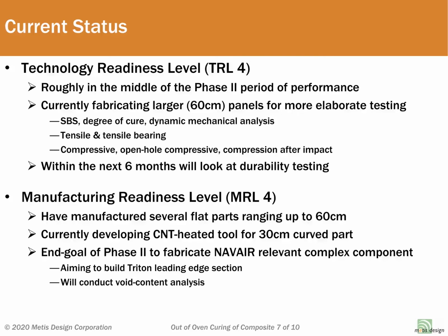We recently completed a series of ASTM tests conducted at an independent third-party test house, including short beam shear, tensile, bearing, compression, open hole compression, and compression after impact. All results verified that our modified cure approach results in components with comparable mechanical performance as those cured traditionally in an autoclave, just at a fraction of the time and cost.